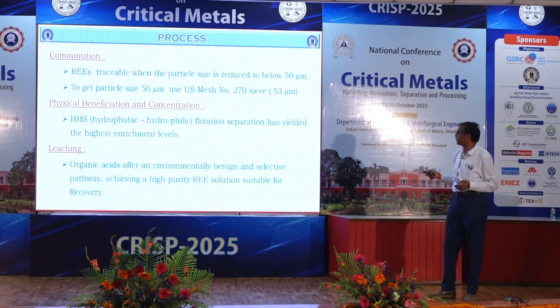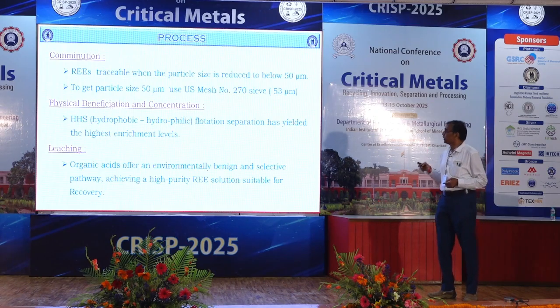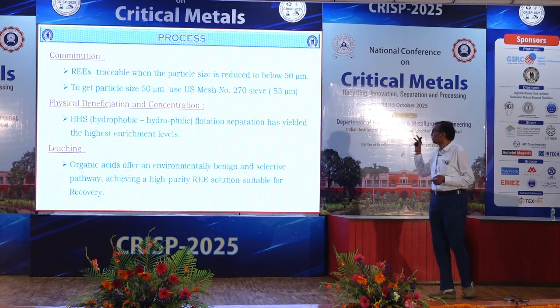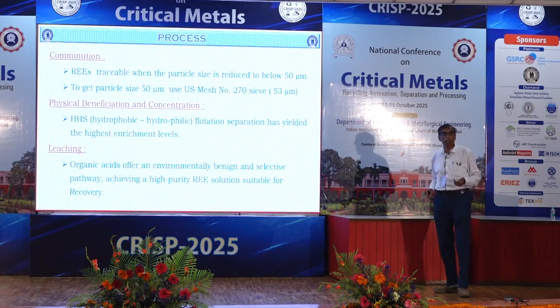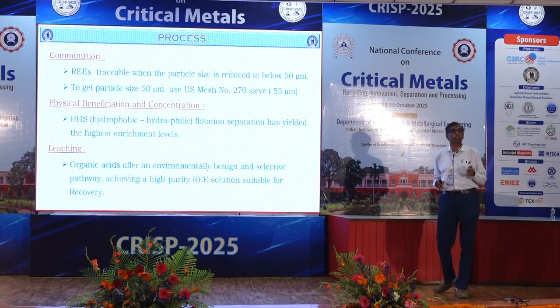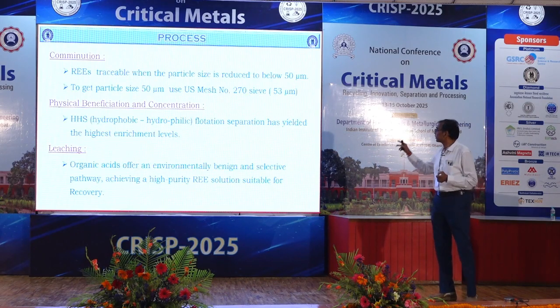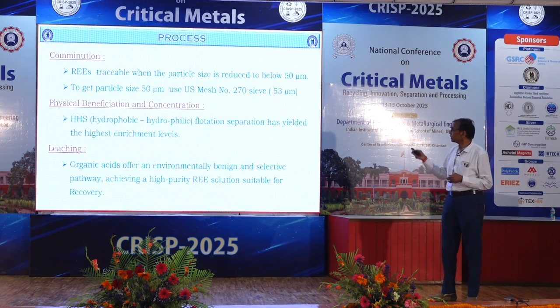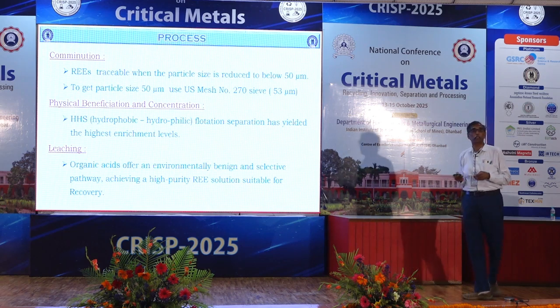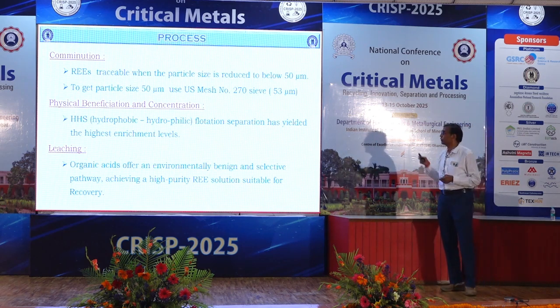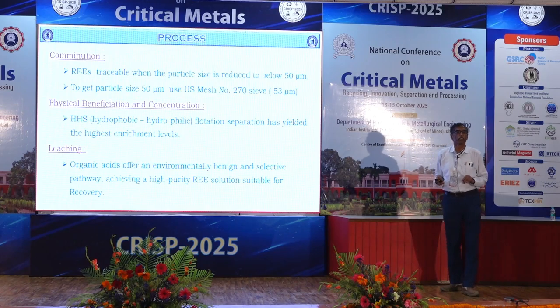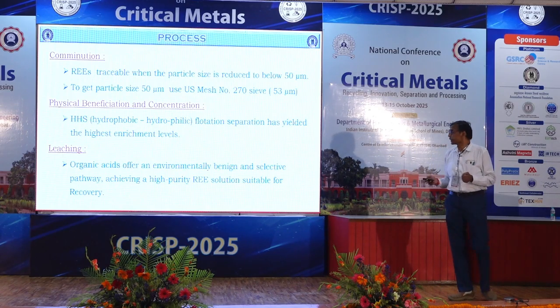So we have done sample-wise work also. The comminution, grinding, is the main thing. Only up to 50 micrometer are these REEs easily identifiable, so that means you have to use the 270 mesh size. Then physical separation, hydrophobic and hydrophilic. This activity has given 10x enrichment in the RE concentrations.